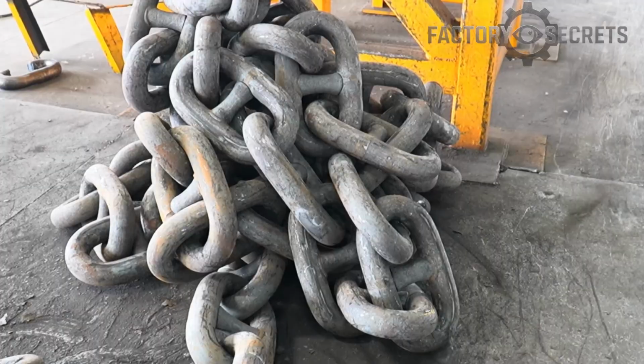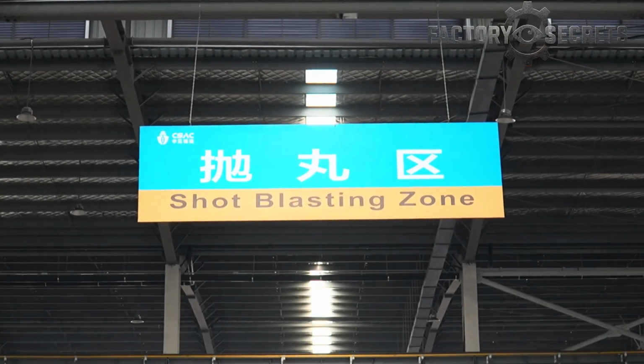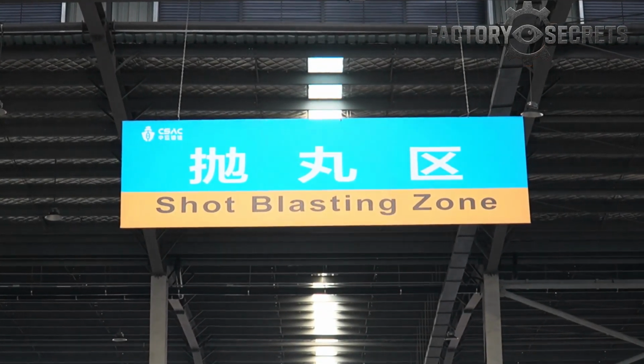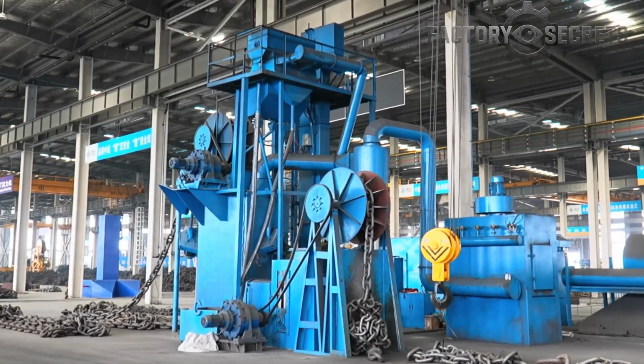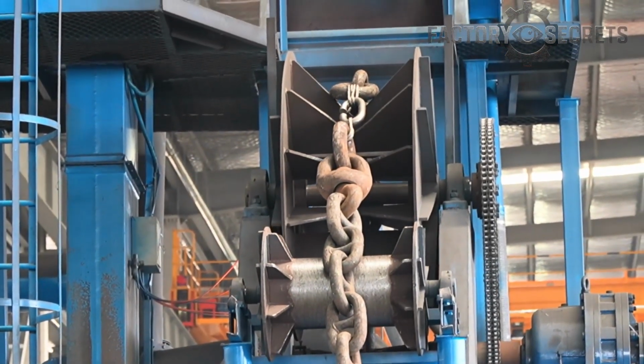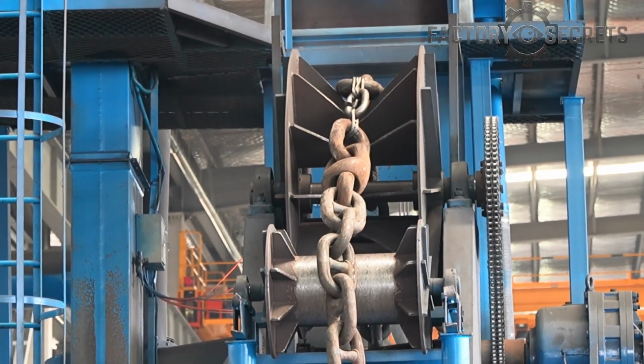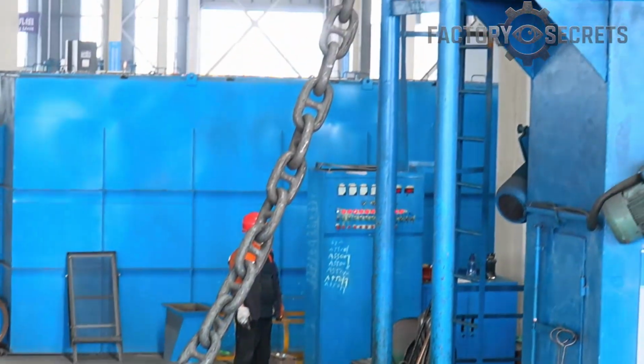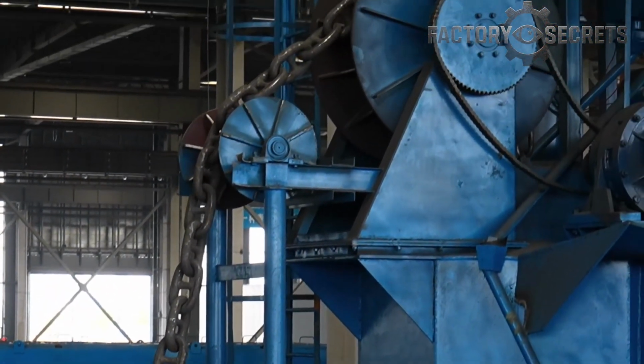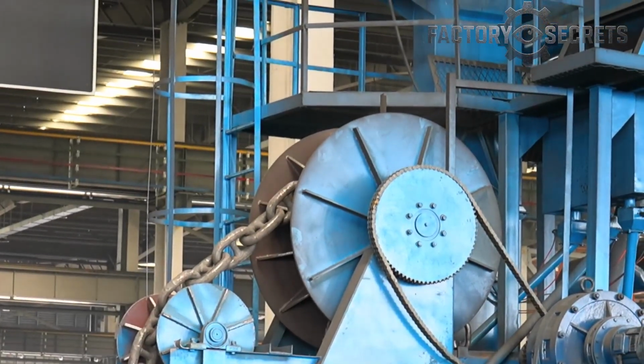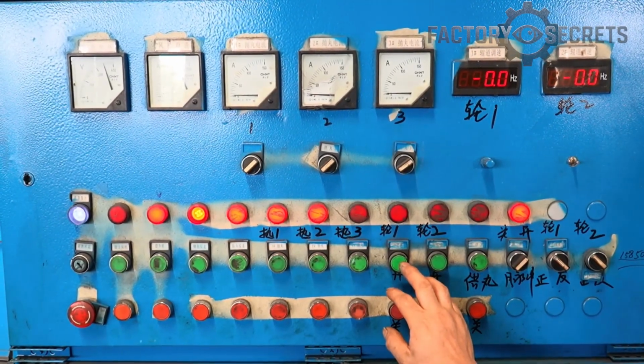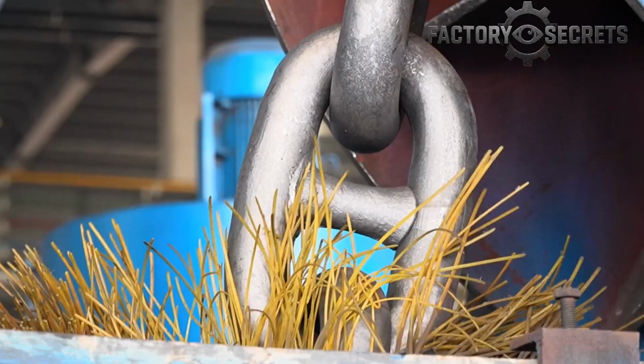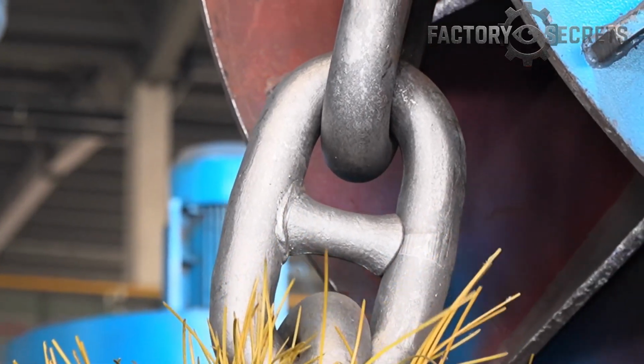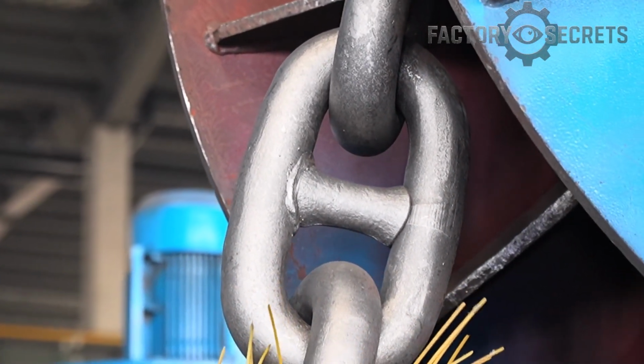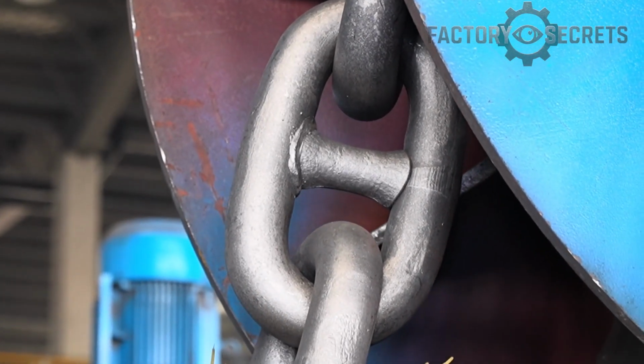With testing complete, the chain moves to the shot blasting zone. And this is where the transformation becomes visible. The chains are fed through a blast chamber where thousands of tiny steel shot particles are fired at the surface at high velocity. Every millimeter of the chain is hit. The scale, discoloration, and surface imperfections from the heating and welding processes, gone. What emerges from the other side is a chain that looks almost new, clean, bright, with a uniform metallic surface.